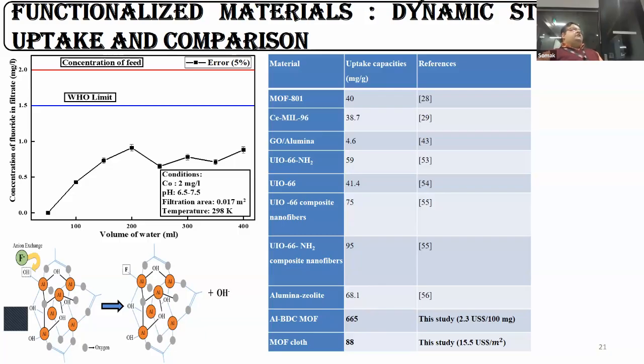We carried out a comparative analysis with different types of MOFs used for fluoride removal, and saw that in most cases, the Al-BDC MOF has high capacity, around 665, with material cost roughly $2.3 per 100 milligram. Whereas for the MOF cloth, the highest capacity is around 88 milligram per gram, and the cost per meter square of this MOF cloth is around 15.5.